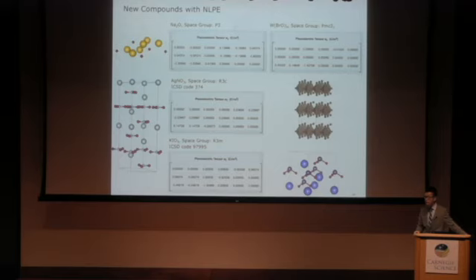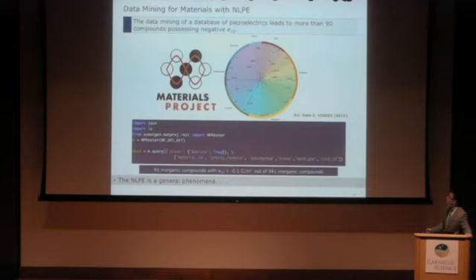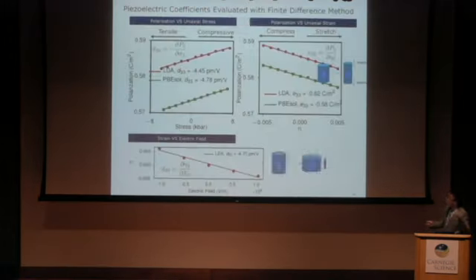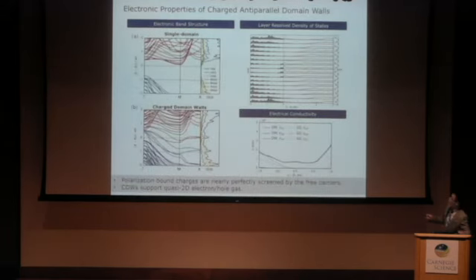I just wanted to go back to your band structure. You showed the band structure for a single domain. Which band structure? The electronic band structure? Yeah, that's right. The charged domain wall part. Okay. Yes. So you showed it just with a single domain, and then you added in the domain wall. Yes. It becomes basically metallic. That's what it looks like. Wow. But my question is, is that band structure a 2D band structure projected onto the domain wall, or is it? Oh, this is just the whole thing. It's the average of the slab. This is the whole Brillouin zone, but it's much better to look at the layer-resolved density of states. If you look at the bulk-like region, it's still insulating, but here it's metallic. Well, at least you have a quasi-two-dimensional electron gas. Yeah, because you write gamma, M, and K, so it's bulk. It's 3D. Okay? So that means that the domain wall has made your whole slab metallic. Well, from the band structure, not from the density of states. Right. Yeah.